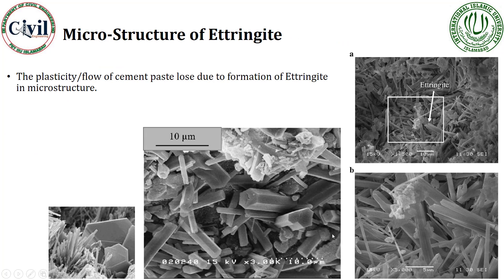Here is a microstructure of hydrated cement. These are micro-level scanning electron microscope images at different magnifications. You can see the ettringite formation as a result of setting of cement at the micro level. The formation of ettringite is a result of the hydration reaction. The agglomeration of these needles causes the loss of flow and loss of plasticity. The cement sets due to the intrinsic property of these ettringite needles.